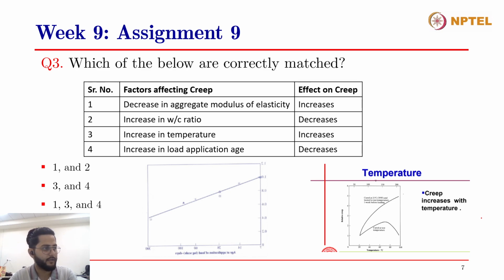Now when the porosity increases, what will be its effect on creep? There will be more space for the movement of water, because the porosity is increased and the pore size has also increased. So there will be more availability of pores of different sizes for the movement of moisture inside the concrete. That will increase the creep. So when you increase the water to cement ratio, it increases the porosity, and therefore it also increases the creep. So except for two, all the other three statements are true.